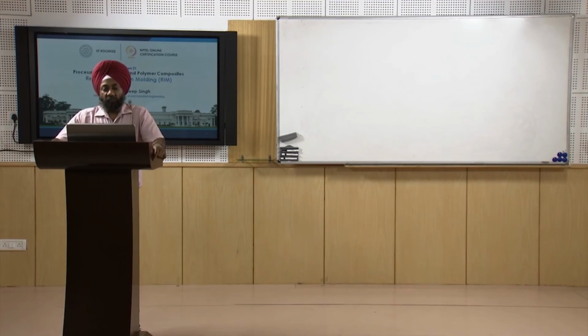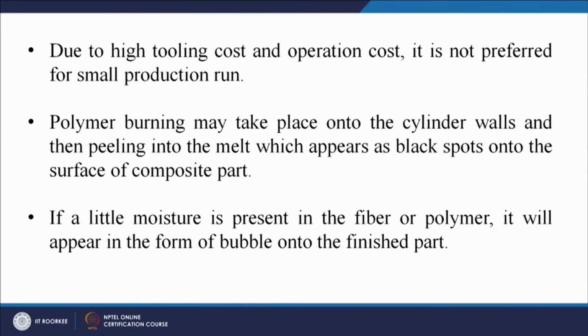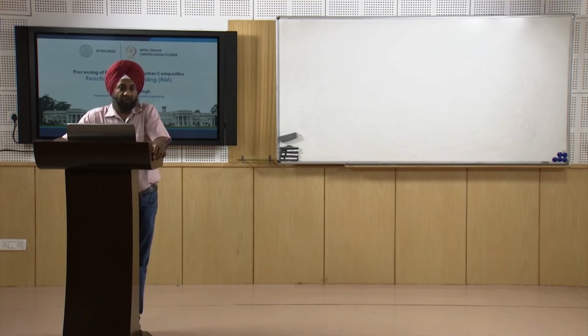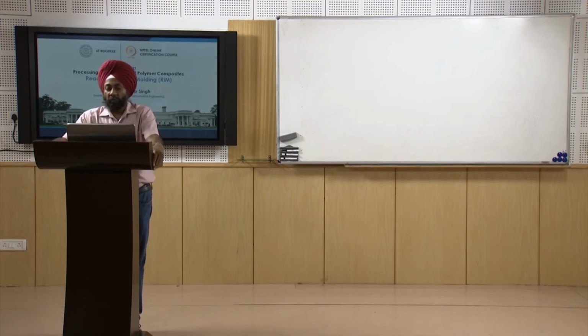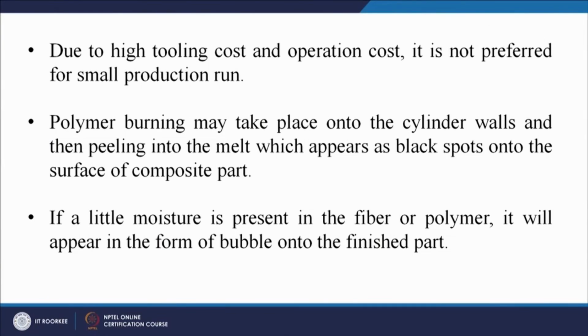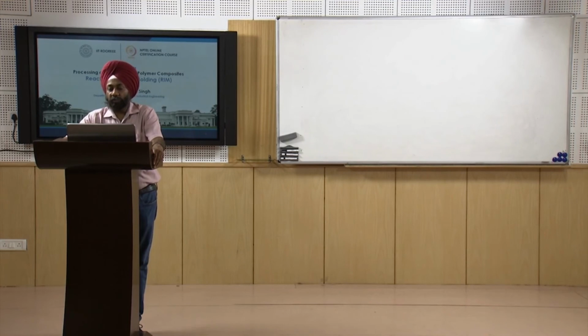So there are a few more disadvantages. Quickly we will go through them. Due to the high tooling cost and operation cost, it is not preferred for small production runs, which was highlighted in the very first slide that we have seen, that the injection molding process should be used for large volume mass production when a large number of parts have to be made. The process is not suitable for a small number of parts. Polymer burning may take place on the cylinder walls and then peel into the melt, which appears as black spots on the surface of the composite parts. Excessive heating may lead to this type of defect, that is black spots on the composite part because of the burning of the polymer, which needs to be avoided.